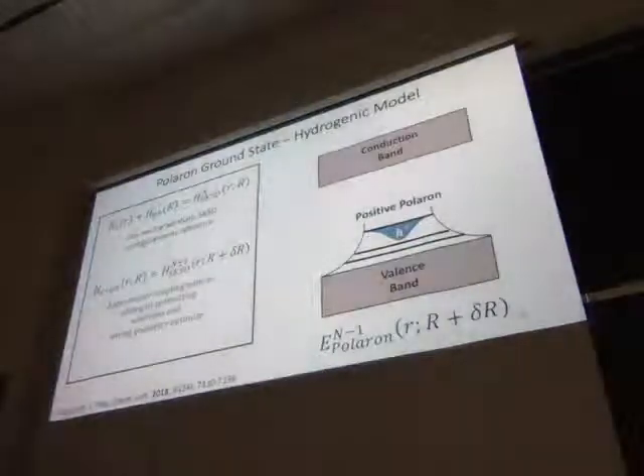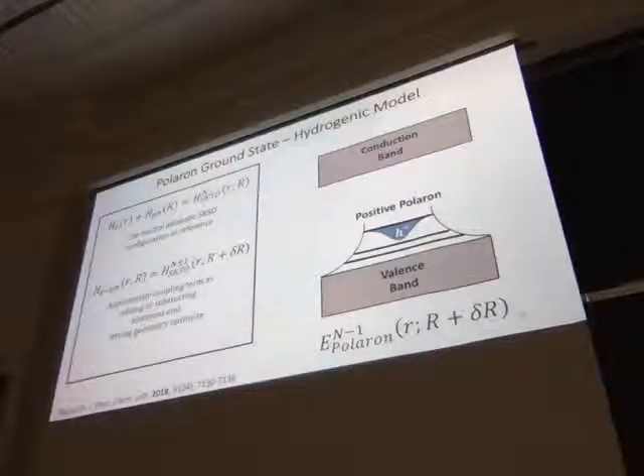And then to model the electronic structure of polarons, we do the same calculation. We start from a neutral model, so that's the independent electronic energy and atomic energy, or phonon energy. That comes from a charge neutral configuration for N electrons. To approximate the cross term, the electron-phonon coupling, we either add or remove electrons from our model system, and then we let the model optimize the atomic positions, delta R, around the new charge. And that's how we approximate polaron formation.